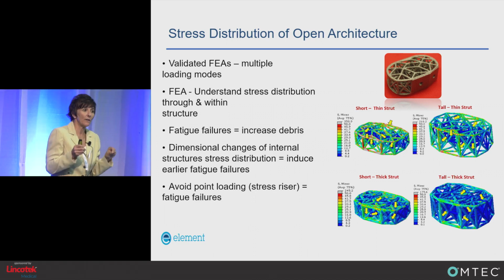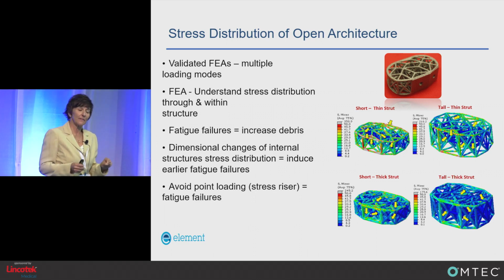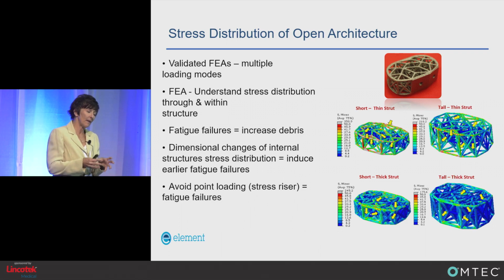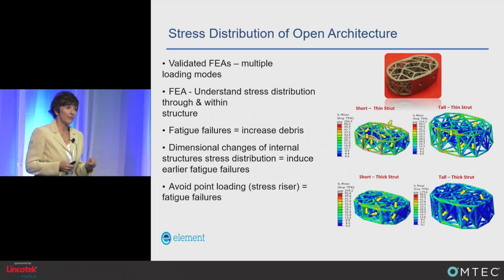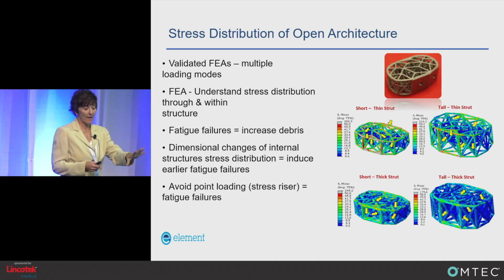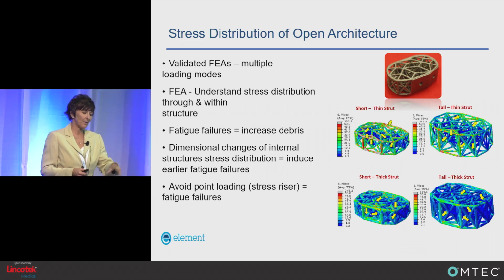Understand how you can model that internal lattice, because in fatigue, sometimes you can have a failure that's a domino effect. If you've got a lattice with thin walls and you've only modeled the outer rim, it could fail miserably. It could fail like a saltine cracker where it'll just shred and you'll have excessive debris. So you really need to understand, how will this stress transfer? And we've kind of done this with some devices.